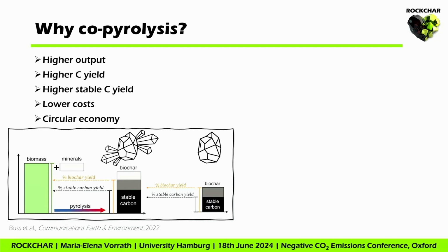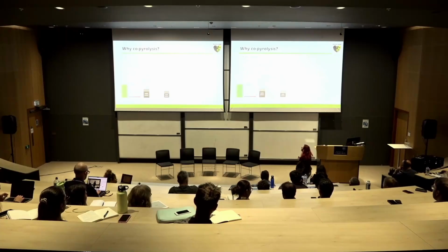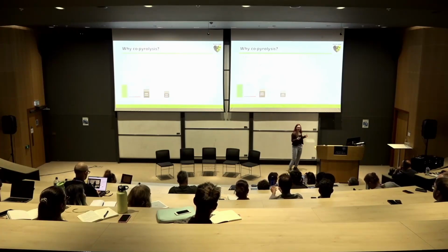And when you add minerals, these minerals do not disappear at 650 degrees, so you get more mass coming out of your pyrolysis. And to give you an example, I have something here. I have one biochar, a normal biochar, and one ROCKCHAR with minerals added, and you can feel that they have a different weight. And we also get a higher yield in carbon and a higher yield in stable carbon. So biochar often contains stable and labile carbon, and the higher the amount of stable carbon, the more carbon will remain in the soil. Very easy. Often, the feedstock of minerals is much cheaper than the biomass, so you can have lower costs, and again, you have the circular economy.